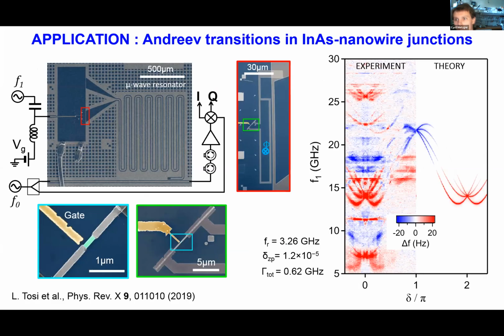Now let's move to indium arsenide nanowire junctions. So in this case, we were measuring single particle transitions that were very far from the resonator frequency at 3 gigahertz. And in this case, the frequency shift was mainly given by the curvature. So here, positive curvature contributes to negative energy shift and the opposite around phase pi.